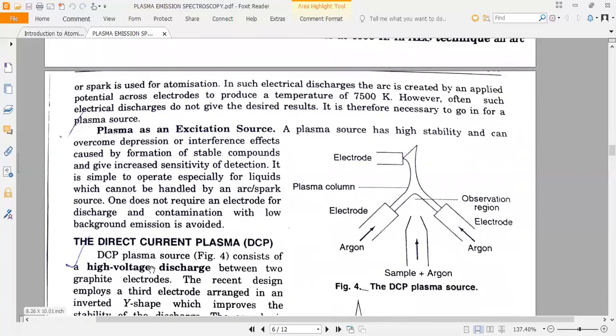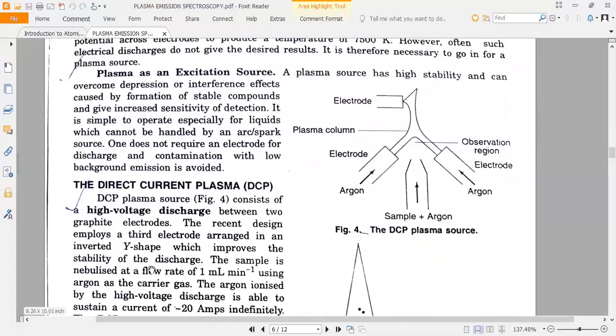First is direct current plasma. You are seeing the diagram here. The description is as follows. The DCP plasma source consists of a high voltage discharge between two graphite electrodes. The recent design employs a third electrode, also arranged in an inverted Y shape, which improves the stability of the discharge. The sample is nebulized at a flow rate of 1 ml per minute. Using argon as a carrier gas, the argon ionized by high voltage discharge is able to sustain a current of around 20 amperes indefinitely.